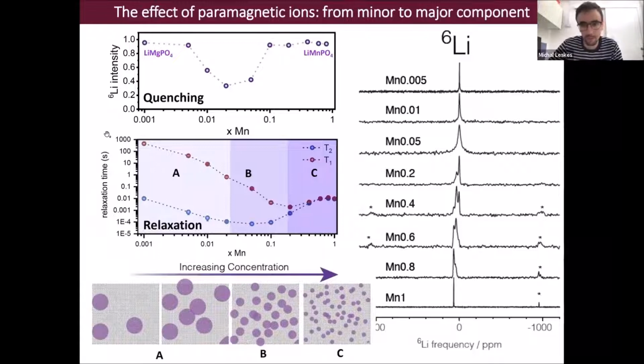And now we think about quenching in the following way. Each paramagnetic center has a quenching sphere around it. So nuclei within this quenching sphere cannot be observed because their T2 relaxation time is just too short. So as we increase the concentration, we're just increasing the volume of quenched nuclei until we reach this section B.